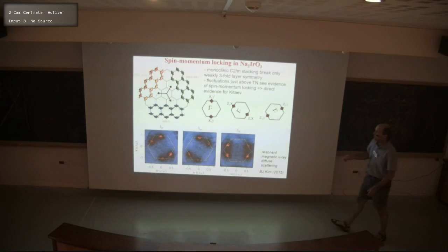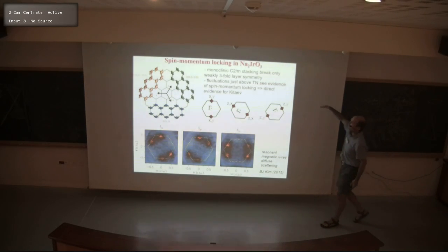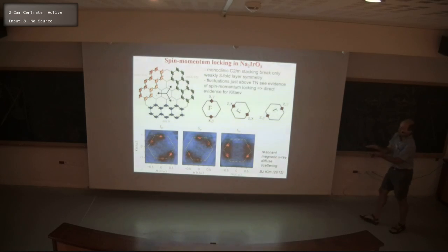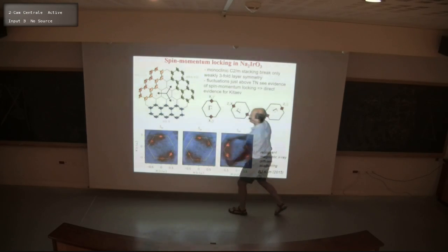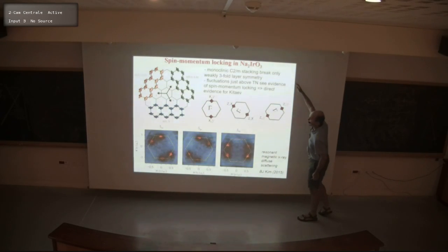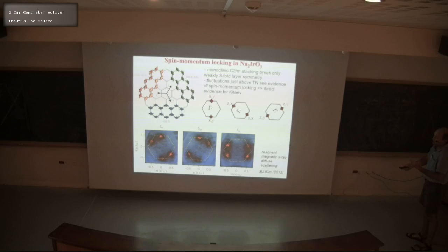So it turns out that this regime can be realized experimentally just above the magnetic ordering transition, because in that case, the system fluctuates, hasn't yet decided the order, and then if the monoclinic breaking of symmetry is rather weak, then the system would fluctuate between the three zigzags. Ultimately, if we go through Tn, it will pick one of them, and it will have Bragg peaks here. But if we're in a regime just above Tn, then it can fluctuate between all three. And here are some measurements of diffuse scattering, looking at the fluctuating spins that sample all these three zigzags from B.J. Kim's group.